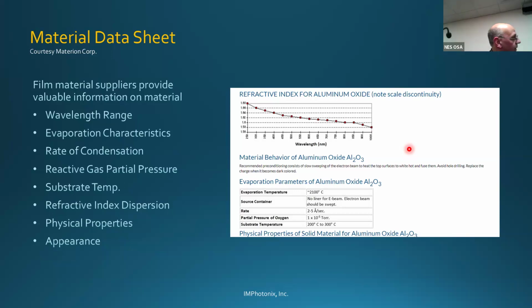The reason why we have to do that is that all of the oxides that the industry uses, when you evaporate them with an E-beam gun, the molecule dissociates. If you're doing tantalum pentoxide, the tantalum and oxygen molecules will separate and they will recondense as a film on the substrate, but they don't always recondense the way that it started the evaporation. So you have to partially fill the vacuum chamber with oxygen. And with the right temperature of the substrate, you hope to form, and this is where a lot of the art comes in, tantalum pentoxide, but not some other film like TaOx.